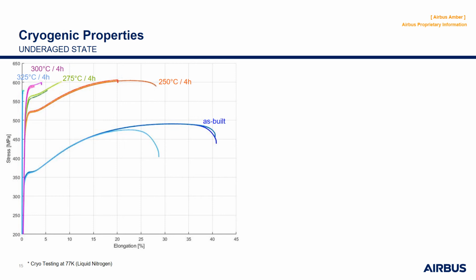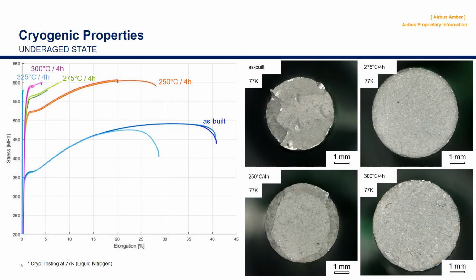The material response to a tensile load at 77 Kelvin is also completely different compared to room temperature testing, as we see a high amount of work hardening in the plastic regime, as well as we do not see any discontinuities there anymore. Another important topic is the sensitivity with respect to material inhomogeneities, which seems to be way more pronounced when testing at cryogenic temperatures.